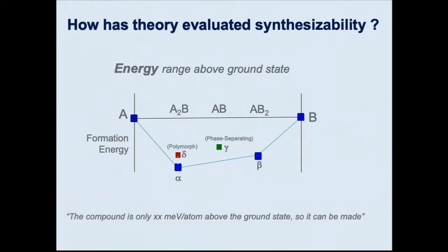Okay. So the first thing I want to do is look at how theorists have thought about synthesizability up to now. And it was all basically determined by energy. We have something that we call the convex energy hull. If you take a binary, you plot mixing energies, formation energies between A and B as a function of composition. And the lowest envelope is what's called the convex hull. These are the thermodynamically stable phases. And then, like here, delta would be a metastable polymorph, right? It has a bit of energy above the ground state. This would also be a metastable polymorph because it would be metastable against phase separation into alpha and beta.